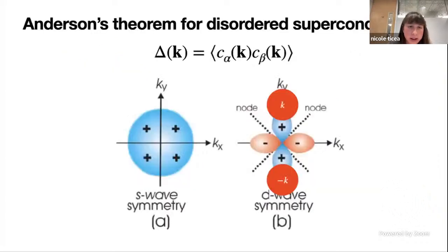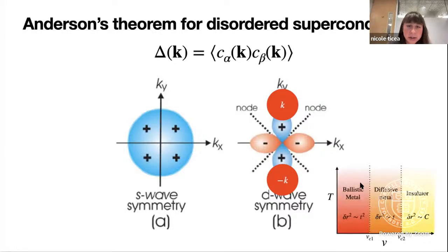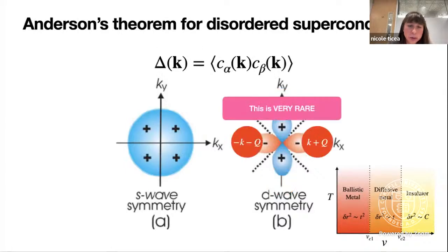Great, okay, so we can return to our sketch from earlier and understand why the ballistic phase of the quasiperiodic system will remain logarithmically divergent at low temperature. That's because if your eigenstates are localized in momentum space, like in this red region right here, then scattering processes will be very rare. As a result, you won't have the same sort of destructive interference that destroyed your Cooper instability in the case of random disorder.